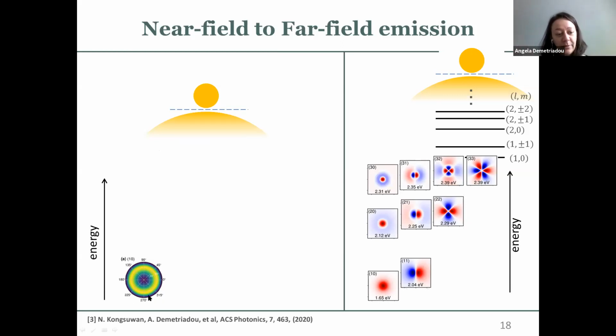So you see basically a donut in the far field. If you were measuring in the far field around the structure, what you would see is emission. This is around 60 degrees. Experimentally, I think it's around 55 degrees. So that's not too far off.